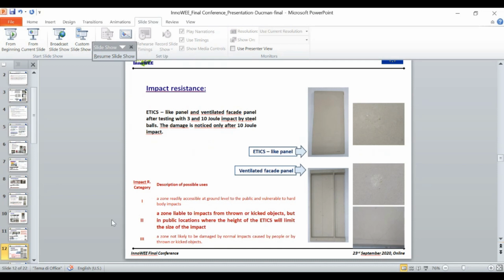The next parameter, which is important when such panels are used in the lower part of facades, is that they withstand impacts from different objects like stones, balls, bicycles, and so on. In order to improve impact resistance, usually a mesh is incorporated into the panels. This was also the case here. As you have seen during the first and the second lecture, they introduced mesh into the panels from pilot production. So we hit these samples with two balls, one smaller and high, and one bigger, to get 3 and 10 joule impact by steel balls.